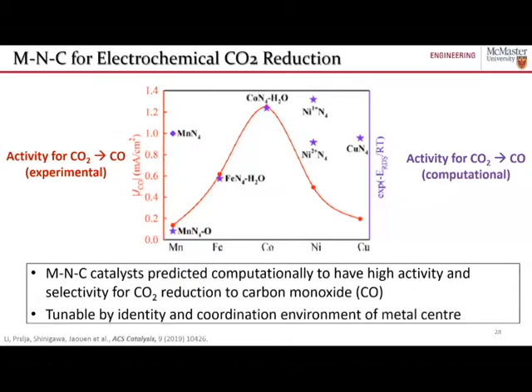But then they also did some computational density functional theory to predict what the activity of these different site structures would be towards the conversion of CO2 into carbon monoxide. And what they found is in some cases, this agreed with the experimental measurements, but in other cases, their computational approach predicted activities that were much higher than was actually realized experimentally. So I think at the end of the day, what this tells us is that the activity of these catalysts can be very tunable by the type of transition metal that's used in them, as well as the particular structure and coordination environment of those transition metals in these catalyst materials. So there's a lot of room for optimization and a lot of room for really understanding how these materials behave and how we can improve upon that performance.